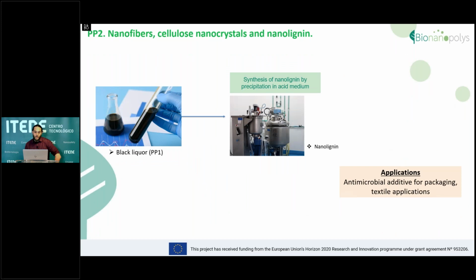The other byproduct that we could obtain, or additive that we will derive from these cellulosic products, will be the black liquor, which could be converted into nanolignin by acid precipitation. That's something that we do here at ITENE in one of our acid reactors. And this nanolignin has important applications as antimicrobial and also as UV protecting additive for packaging and textiles.